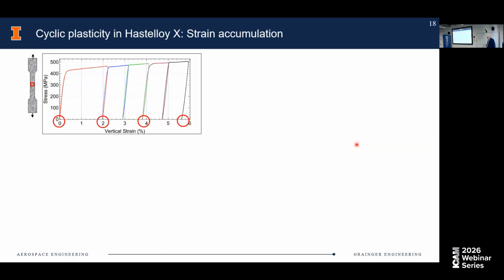So some typical results. First, let me start with cyclic plasticity. Understanding cyclic plasticity is almost essentially a precursor to understanding fatigue, because fatigue really is an outcome of plastic irreversibility. If everything went back to where it started from every cycle, there would be no fatigue. So essentially what we do here is a series of loading, unloading experiments on a particular material. Again, this was in terms of the Air Force funded project. So it was a nickel superalloy, Hastelloy X, that we were looking at.